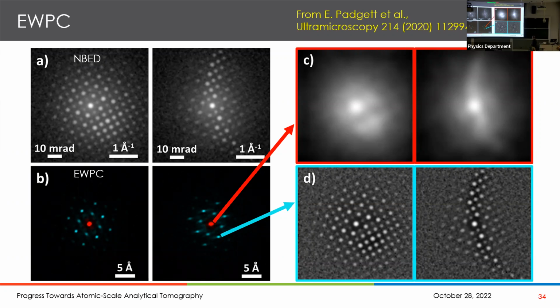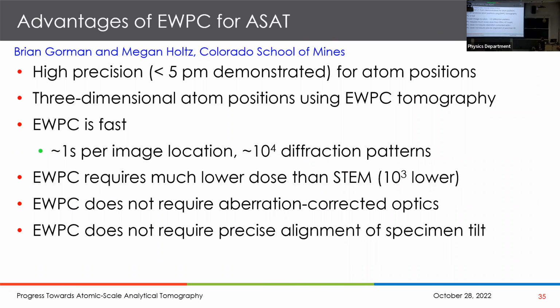At any rate, the bottom line is here that this approach, as I say, that Brian and Megan have been developing, has demonstrated better than 5 picometer precision for the atom positions. It's a mind-blowing precision, but I've seen this multiple times. And you get the 3-dimensional positions of the atoms from this approach. And I'll show you another example in a minute. And it's fast, if you have a fast camera, that is. So you're looking at something like 10 to the 4 diffraction patterns to cover an area. And that can take all of a second to record. And then you've got a little bit of number crunching and you're done. Another really important point is it requires about 1,000 times fewer electrons than if you tried to record that similar information with the standard STEM approach.